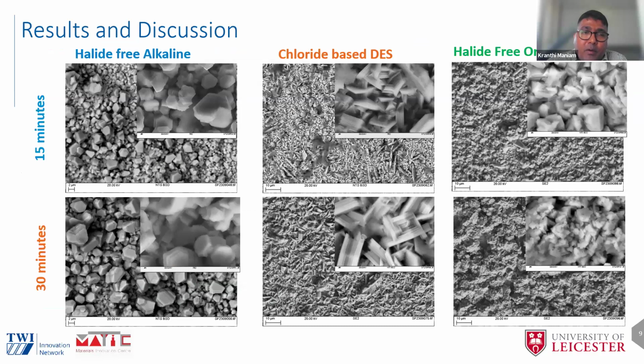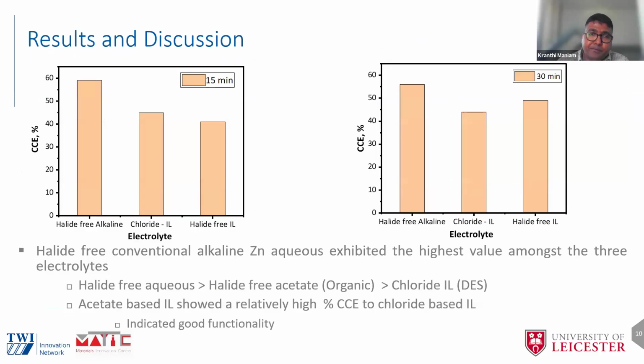We all know that zinc has a hexagonal structure, which is the main reason why you get good corrosion protection. You can see that with an increase in time, the orientation is changing with regard to the deep eutectic solvents and the halide-free organics. That depends on the transportation of the species, which is why you see a different orientation of the planes. But still, you can see that oriented hexagonal planes are formed.